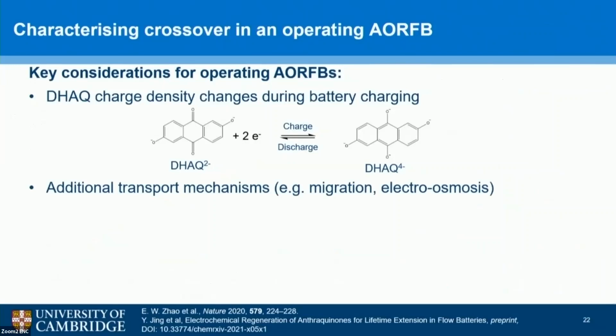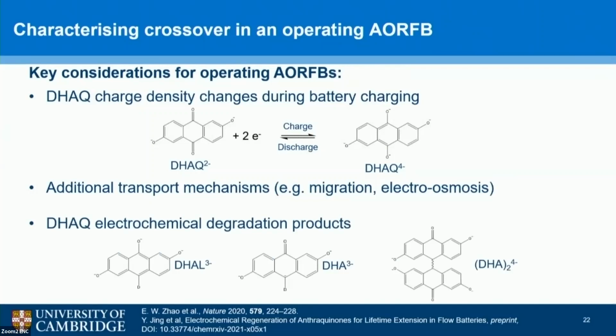However, there's also other additional transport mechanisms to consider. So we have migration, which is basically where the quinone itself could be used as the charge balancing species. So when you charge the battery, this could be a driving force to increase crossover. We also have things like electroosmosis, which is where the water gets dragged in with the ions. And then we also have electrochemical degradation that you wouldn't normally see in a normal diffusion experiment. And these are just a few examples that have been reported previously.